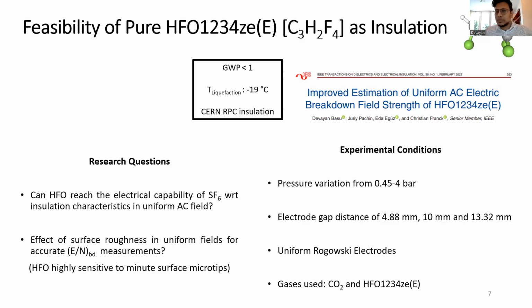For this, in the experimental conditions we varied the pressure from 0.45 to 4 bars, because beyond 4 bars, HFO started to liquefy at that temperature. Then we used electrode gap distances of 4.88, 10, and 13.32 millimeters. The electrodes used were uniform Rogowski electrodes. And the gases we used were, of course, pure HFO, but also CO2, and we'll see in the next slide why we need the CO2 in the first place.